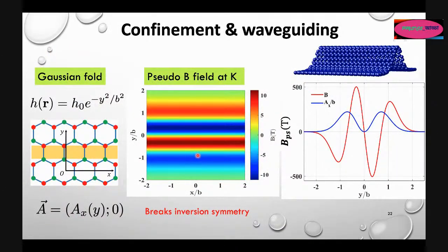We can do something similar for extended deformations, for ripples and folds. And in this case, the shape of the membrane looks like this. If I represent the shape with a Gaussian, I can again repeat the procedure that I told you before and obtain the form of this gauge field. And this gauge field changes in position, so it gives rise to a pseudomagnetic field. And here I plotted the profiles of the pseudo gauge field and the magnetic field.